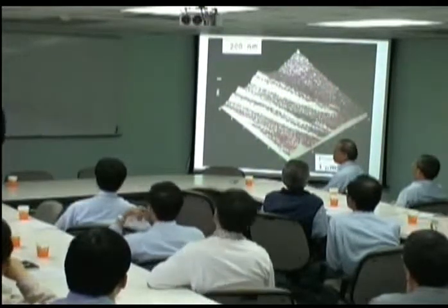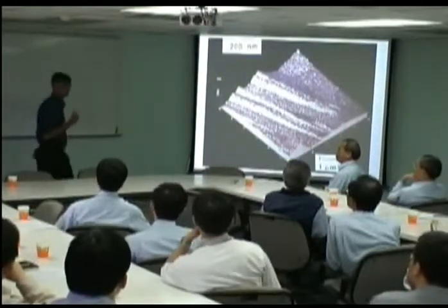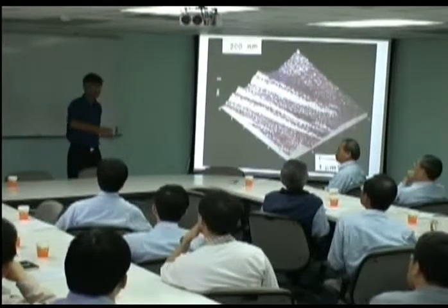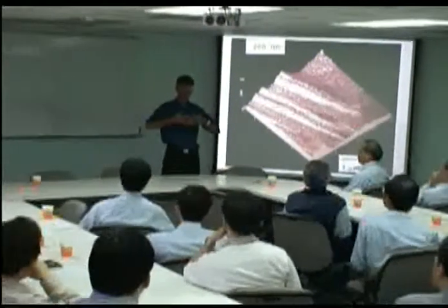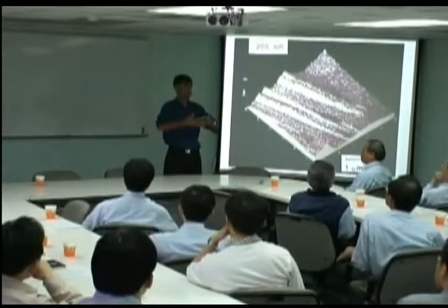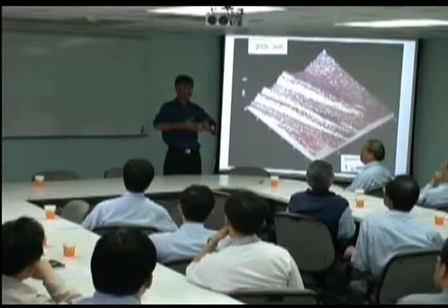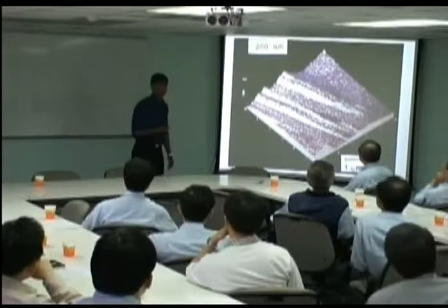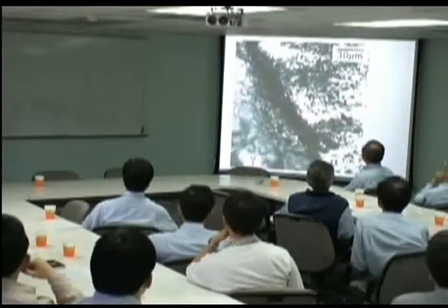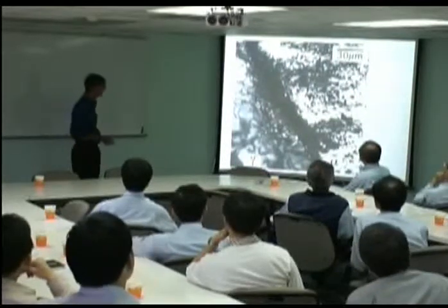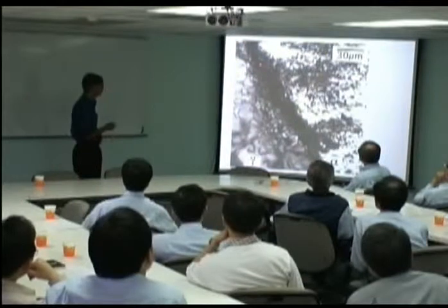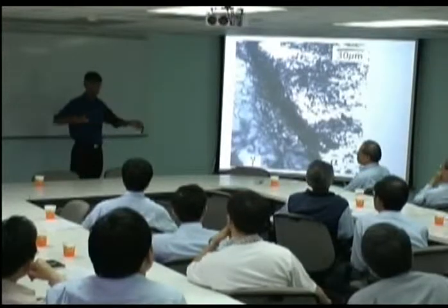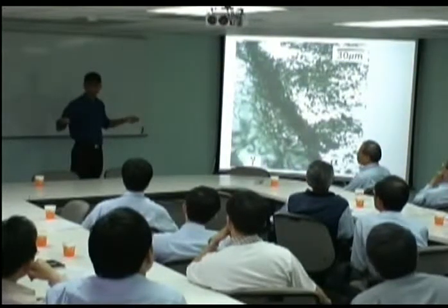It has a very large effect because when you have a displacive transformation, if you put any obstacles in its way, you will retard that transformation. Because the interface consists of a set of dislocations. Any obstacles you put in the path of the dislocations will stop that interface. So this deformation, which is generated by the bainite, actually stops this plate from growing. And in a transmission electron micrograph, this is the interface here between the austenite and the bainite, and you can see a huge array of dislocations. That basically prevents the interface from moving once it gets to a critical density.